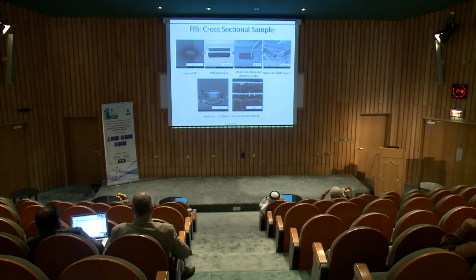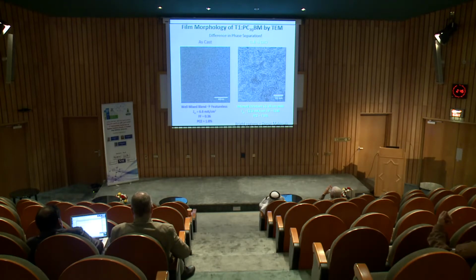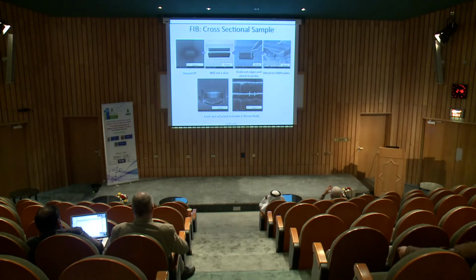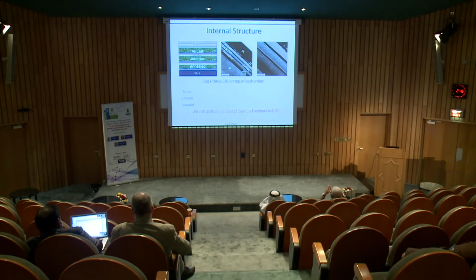And so next, we also look at the internal structure of the film, because the data I showed you is basically top-down, where you transmit an electron beam through the film, and a lot of people are skeptical about whether the internal structure or internal morphology of the film looks the same as the top-down one. To do that, we take our devices and use a focused ion beam to cut a thin slice, about 15 microns in length, 5 microns in width, and 100 nanometers thick. We transfer that slice, as you can see in the top right image, using the micromanipulator. We transfer it onto a TEM grid, and we look at the internal structure of the film.